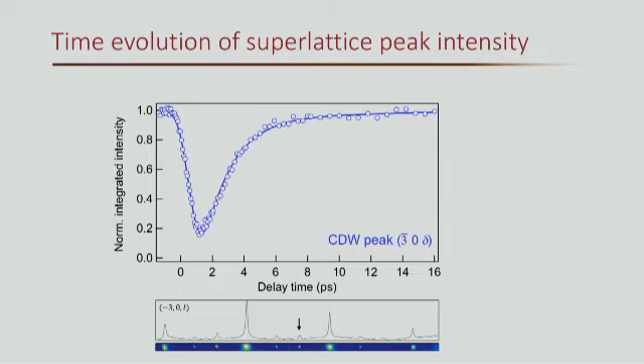For this particular excitation fluence we use, the characteristic timescale of the decrease is less than 1 picosecond, and it is below our time resolution in the instrument. And relatively quickly, it takes about 1.8 picoseconds to recover. Let's pause a little bit to really look at this diagram and see what's going on in the material, specifically in terms of the lattice movement. So why does this decrease?